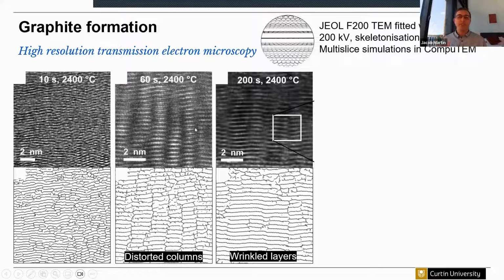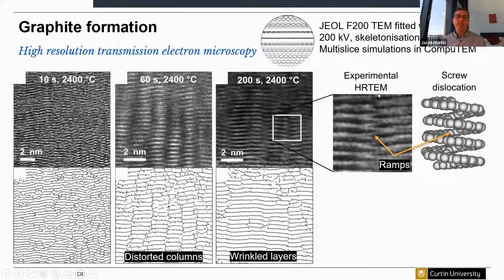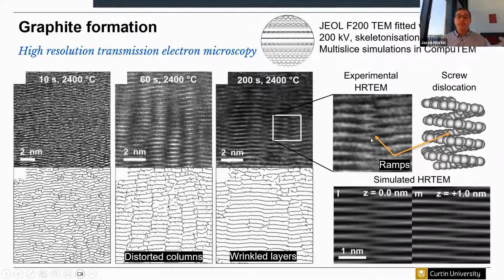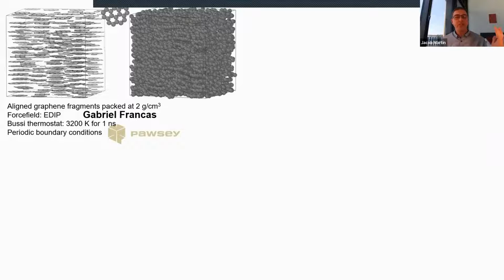So, I mean, graphite's easy to image in the TEM, so it's not the most remarkable thing, but they're quite nice images of graphite. And then when it came to quite a few pulses, we found some interlayer defects that were very consistent with a screw dislocation. And these hadn't been imaged before, particularly this ramp between the layers. And we're pretty sure that those are screw dislocations. Now we kind of came to the point of thinking, how do these actually form? And what role do the screws play?